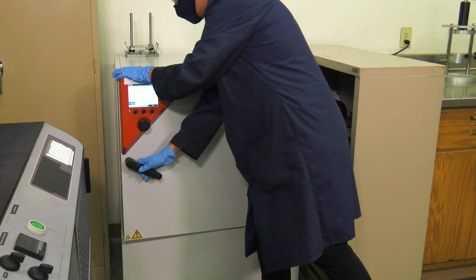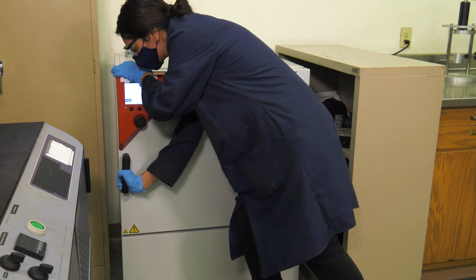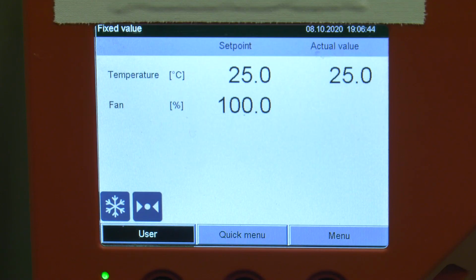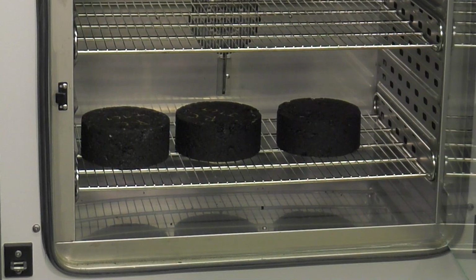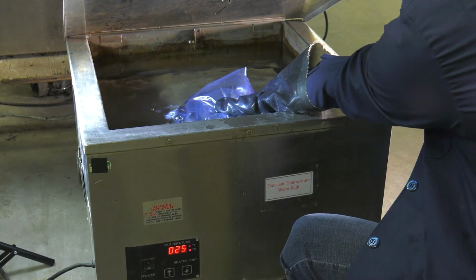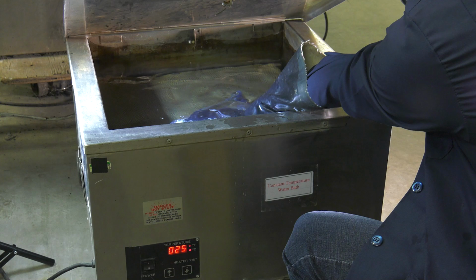Condition test specimens in an environmental conditioning chamber or water bath at the target test temperature for 2 hours plus or minus 10 minutes. If water bath is used, use a sealed bag to prevent moisture ingress to the test specimen.